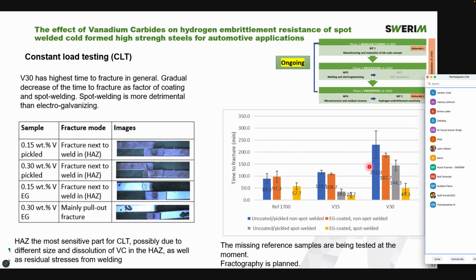We can also see that the coated material in most cases lasts for a shorter time than the uncoated material. This is probably because there is a galvanic reaction between the zinc coating and the steel of the bulk material on the sheared edges, and that reaction can produce hydrogen, which in turn can affect the results of those tests. We can also see that the spot welded material performs worse than the non-spot welded material in both coated and uncoated conditions. This is possibly due to the different size and dissolution of the vanadium carbides in the heat affected zone, and it could also be due to residual stresses from welding. To better understand this behavior, we will perform fractography analysis on the samples.